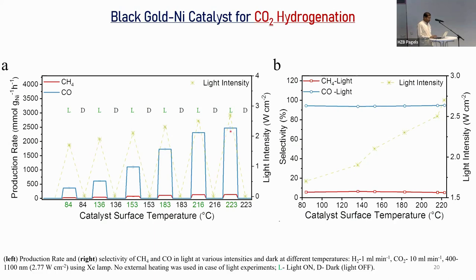Another interesting thing is, when you expose the black gold to light, the electron goes to the excited state and comes back, and another batch of hot electrons relaxes back and hits the vibrating atom and converts that entire energy into heat. And that heat we measure is around 223 degrees Celsius. How we measure the temperature: we took a thermocouple and inserted it into the black gold while it is exposed under light. So that's the temperature of that black gold powder, and it was 223 degrees Celsius. When we carried out the same reaction without light, in the dark at 223 degrees Celsius, activity is zero. There's absolutely no activity, indicating that it is the hot electron which is carrying out these reactions and not the heat. I will come back to this point again.